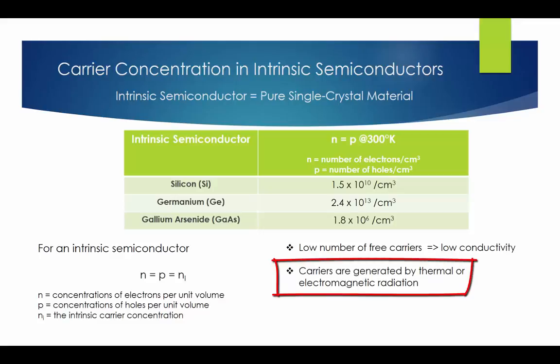At elevated temperatures, some covalent bond electrons get thermal energy and escape from their bond, thus become carriers. However, in an intrinsic semiconductor, the carriers are in very low numbers. It looks big in absolute value, but compared with the total covalent bond number in a crystal, that's just one broken bond in every 10 to the power of 13 bonds. Thus, at room temperature, intrinsic semiconductors have very low conductivity.